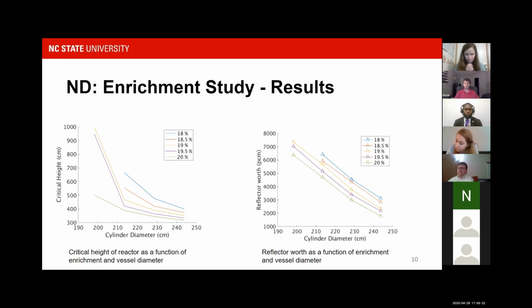The reflector worth decreases as a function of vessel diameter, and the reason is that the size of the reflector shrinks, because we define the size of the reflector to be equal to the height of the cylindrical section. As we increase the vessel diameter, we decrease the amount of radial leakage out of the core, which also decreases the critical height of the core as well as the reflector worth. So we set a limit on our vessel diameter by limiting the decrease in the reflector worth, so that we would have adequate shutdown margin for our design.